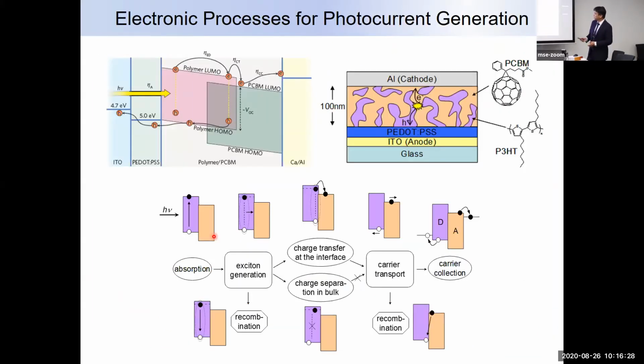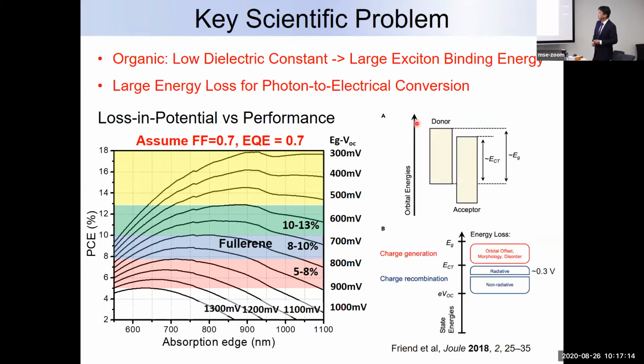One of the reasons why we want to make this bulk heterojunction is that the exciton generated in organic material is a Frenkel exciton. They are very localized. So if you cannot find an interface between the donor and acceptor materials which has enough energy to separate the exciton, they will just recombine and be lost. Therefore, you need to create this nanophase separation with a length scale in the 10 nanometer range. And they need to have a continuous path so that the hole and electron can be carried to the two different electrodes. So this is the important process for photocurrent generation in a bulk heterojunction solar cell. And of course, the low dielectric constant and large exciton binding energy set some limitations for organic solar cells.